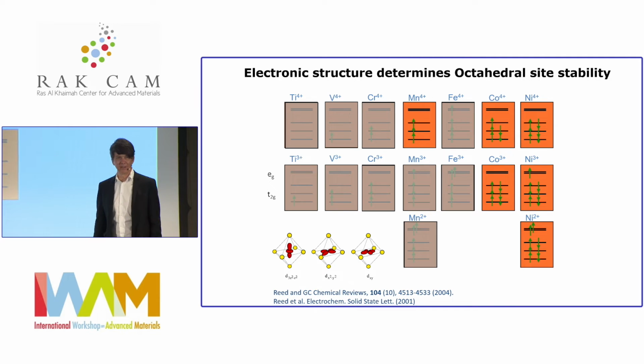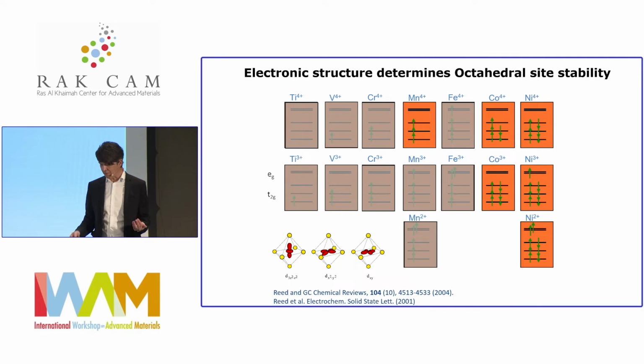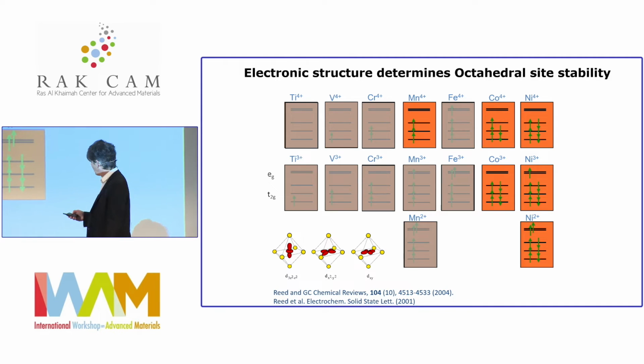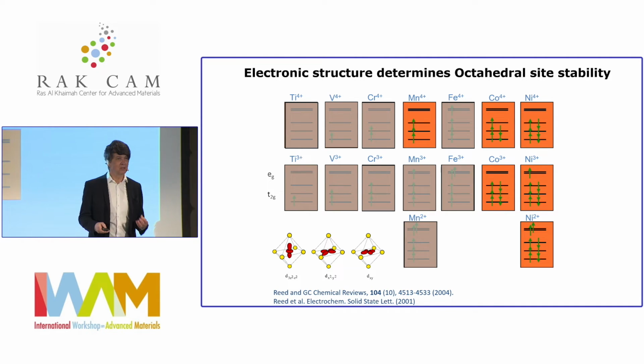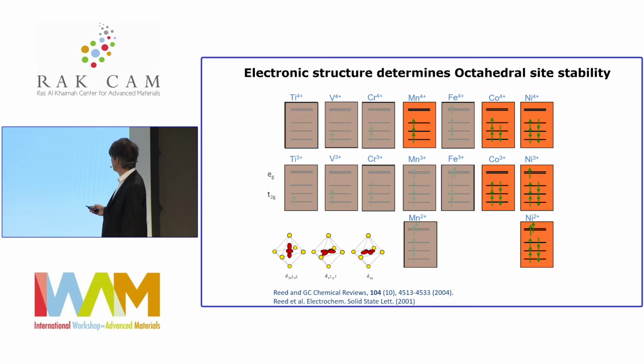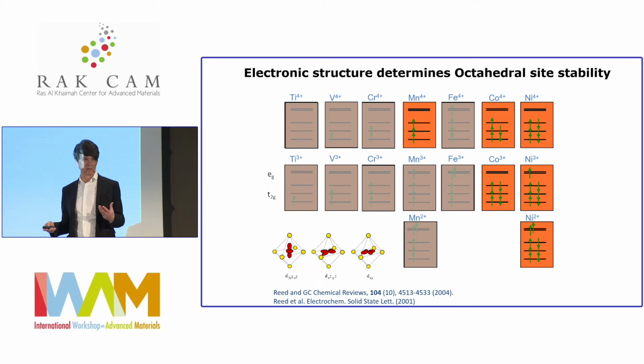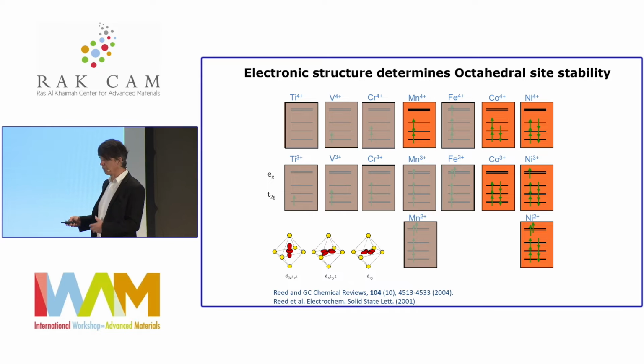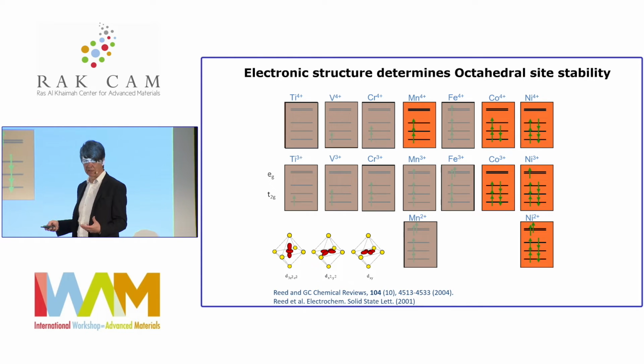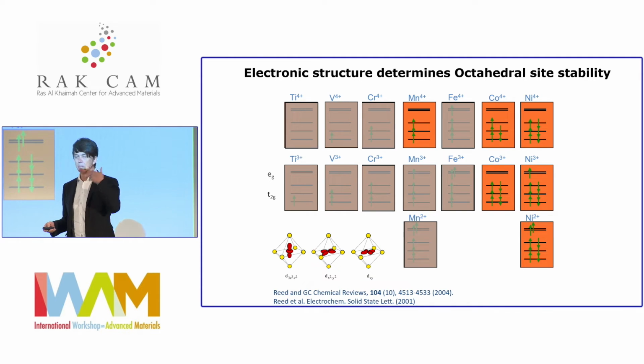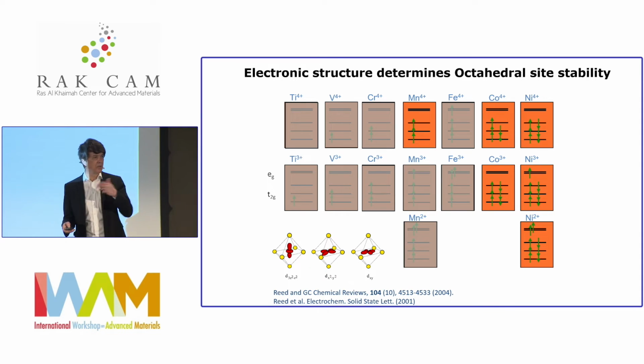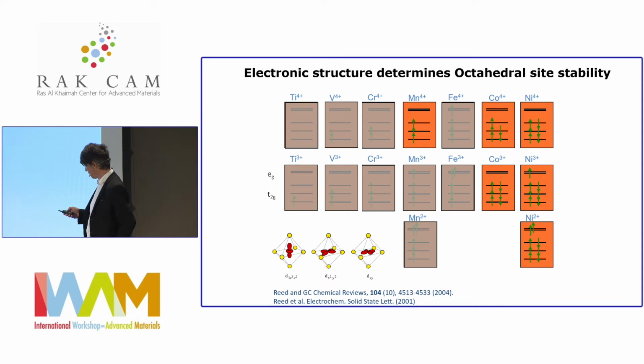So here's the periodic table that we have left of the 3d metals. It's basically nickel, manganese, cobalt, NMC. This is why batteries are NMC. The best ion by far, and this was Goodenough's brilliant discovery, is cobalt 3 plus, 6 electrons in low spin configuration. So you have this massive octahedral ligand field stabilization. Cobalt is an ion that on the time span of 100 years does not even make a single hop when you do the calculation. So it's a brilliant material, lithium cobalt oxide. Cobalt never goes anywhere, even when you fully delithiate that material.